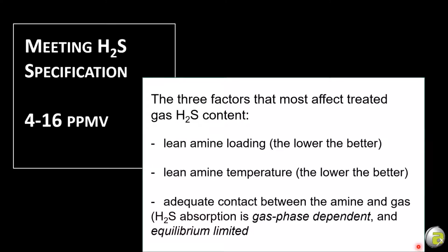As far as H2S spec, in most jurisdictions in the world, we're trying to meet less than 4 ppm, sometimes 16 ppm allowable, but with most gas processing, we're trying to reduce the H2S to extremely low levels to sell it. Now, if we want our amine to do the best job possible of meeting that tight H2S spec, there's 3 key things that we have to pay attention to. The first 2 we'll call the quality of the amine. So the quality of our treated gas is how low is that H2S spec that we're making, and the quality of the amine is the loading and the temperature of the amine that feeds the top of that tower.